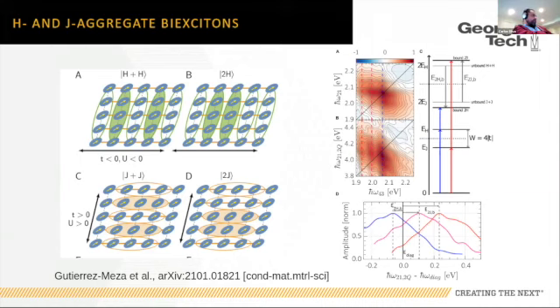In the Wannier biexcitons, the photoluminescence signatures were very easy. You do a fluence-dependence PL measurement, and then you see peaks that grow in with fluence with quadratic dependence, and you assign them as a biexciton, and they're very spectrally well defined. That doesn't appear to be the case in these systems, largely because of heterogeneity, but also I think what we might begin to understand from this is that there's a very complex set of correlations, where it's not clear whether you should always get a red shift or a blue shift, and they may be small, and on top of our large and homogeneously broad linear line shape, so they're probably very difficult to make out. And so that's my sort of gut answer.